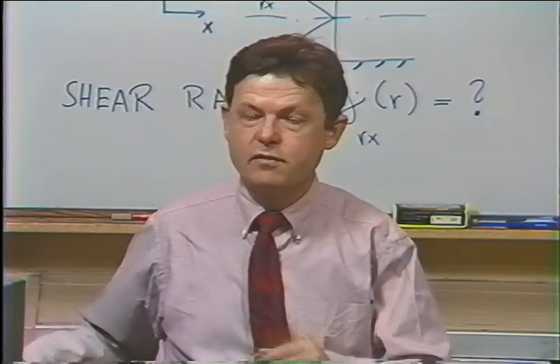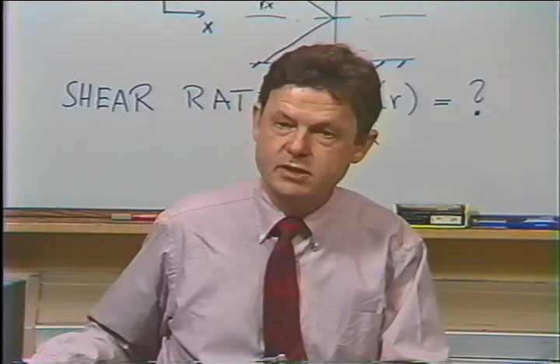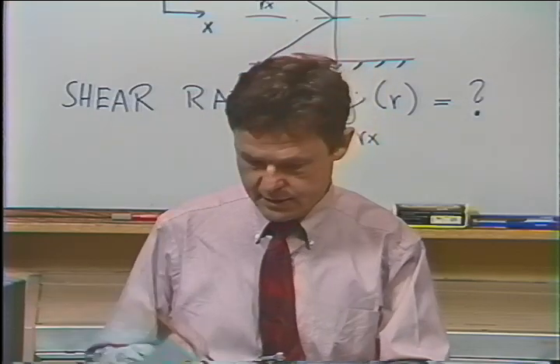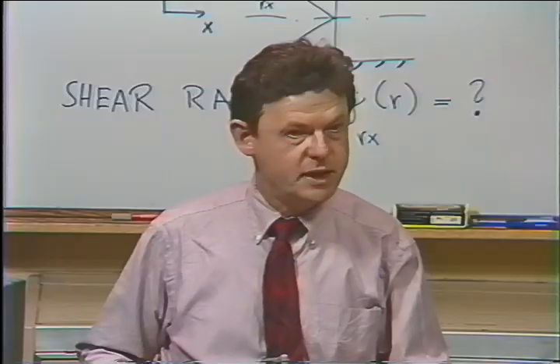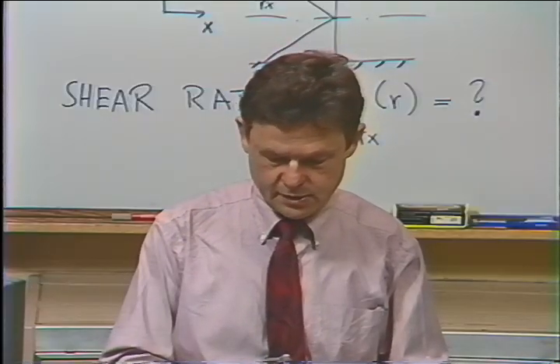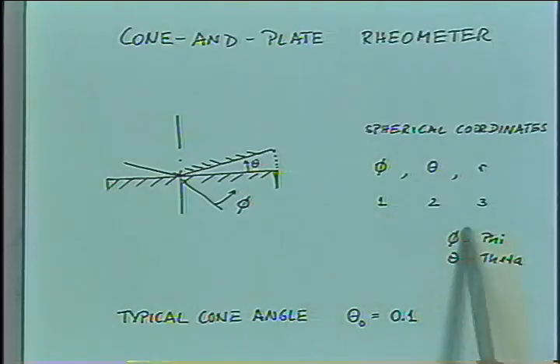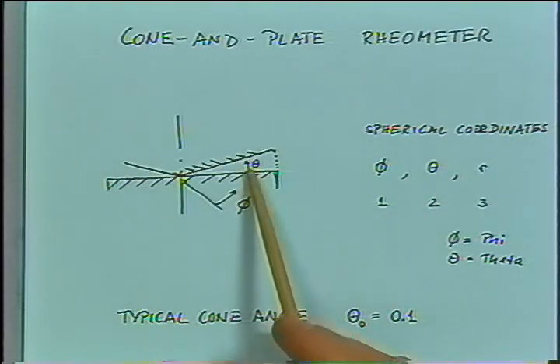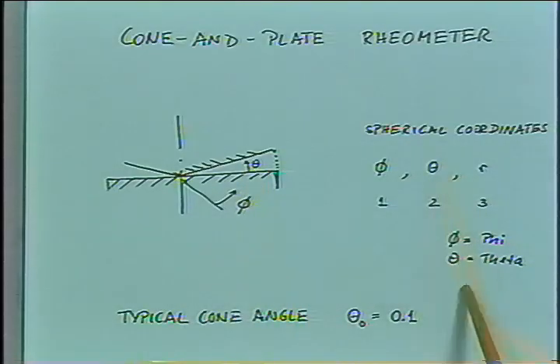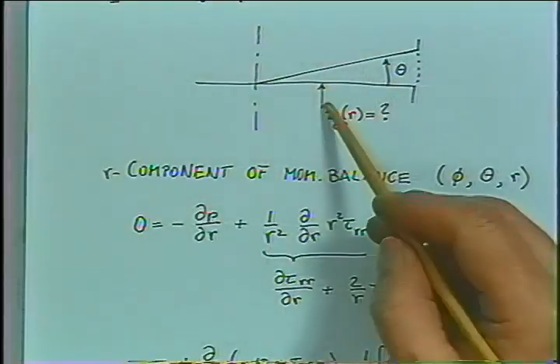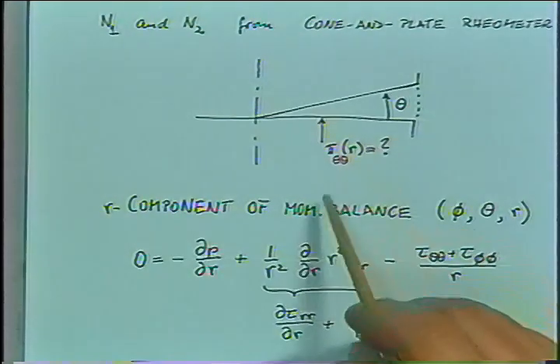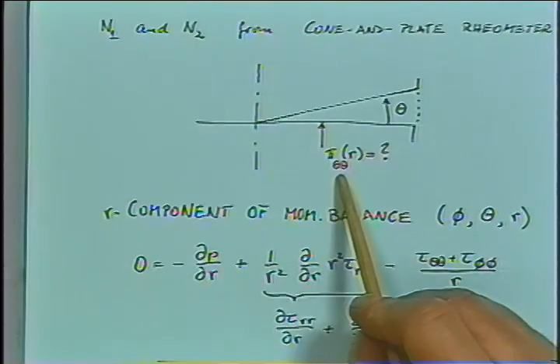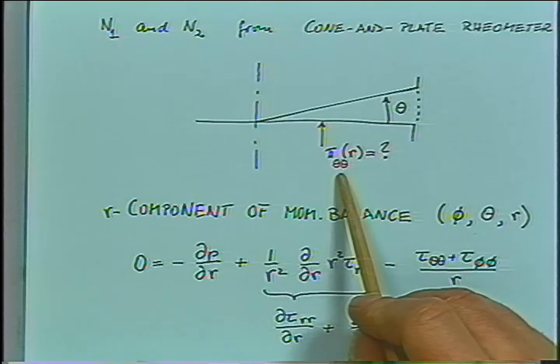Interesting is the analysis for the normal stress measurement in that system. It goes back to Weissenberg in the 30s. For that analysis, we will use a spherical coordinate system where the 1 direction is the flow direction. This is the phi coordinate. The velocity gradient for the shear flow is the theta direction, and 3 would be the radial direction of that geometry. And again, the angle is very, very small. In our analysis, we would like to know what's the normal stress in the 2 direction. What's the normal stress on the plate due to the flow in that system?